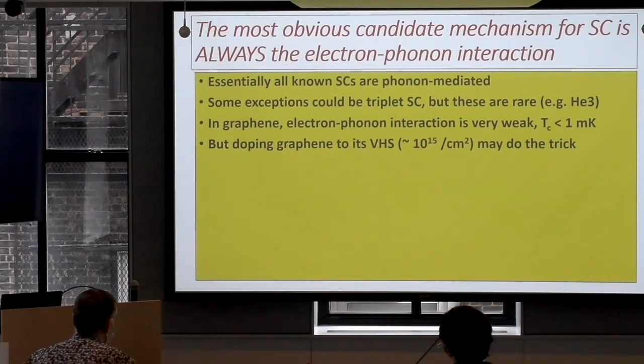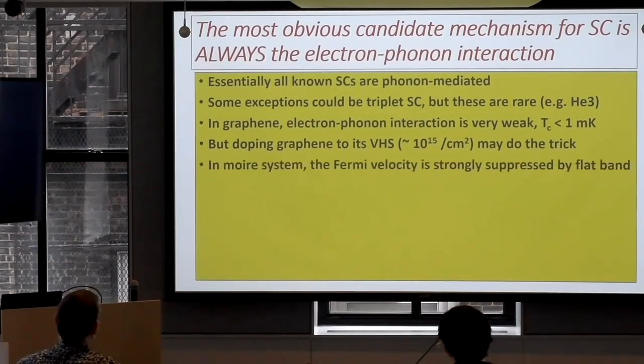I don't disagree with this, obviously, but this is not what is going on in graphene. I think at least nobody has shown it. So, why is electron-phonon interaction in graphene important at all? Because in real graphene, just monolayer, Tc is very low, as I told you. What happens in Moiré systems, and this was really the only insight I've had, because Andrea Young called me and asked me why their resistivity is so large, 1,000 times larger than monolayer graphene, and it's linear.